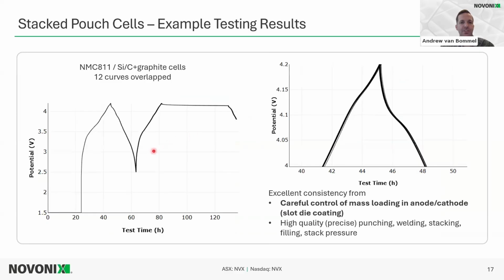So here's some example testing results from some of our stacked pouch cells. Here's some NMC and silicon carbon. Silicon carbon and graphite is in the anode for these cells. These are 12 formation curves, the same formation that I showed before. So these are 12 curves overlapped, and you can see that this is excellent control, excellent consistency within those cell groups. If we zoom into this section here, we see very little differences in test time, which would correspond to very little differences in capacity.